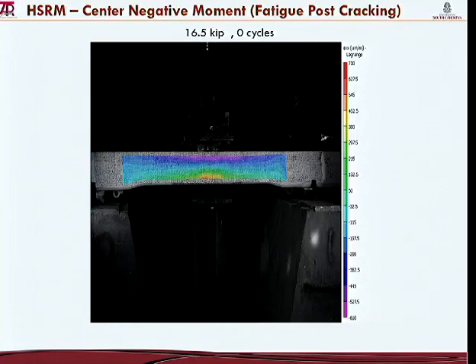So we can see here the evidence of the crack as the number of cycles accumulates. Load is always 16.5. Notice that the crack propagates a little bit, but then it stops. And notice how the strains spread out. So we have load redistribution, which is a desirable effect. This is what we would like to see. And then that's it. Nothing else happens to it, so the performance is maintained.